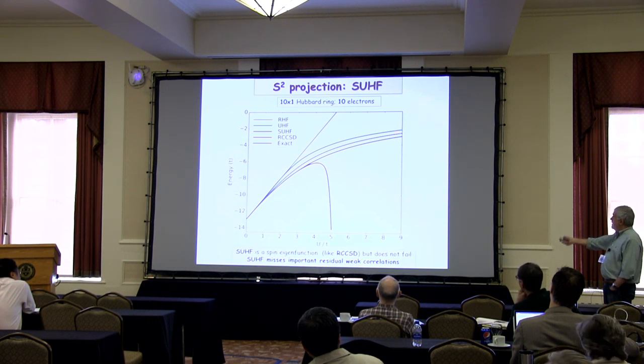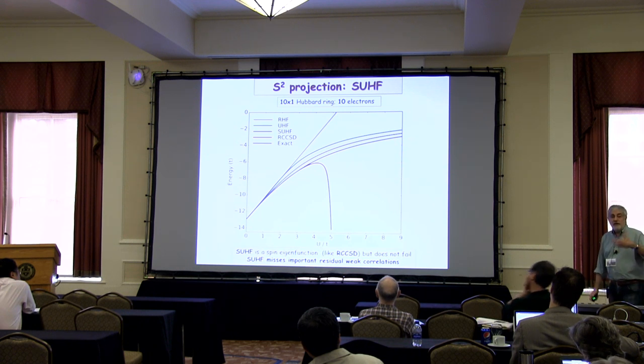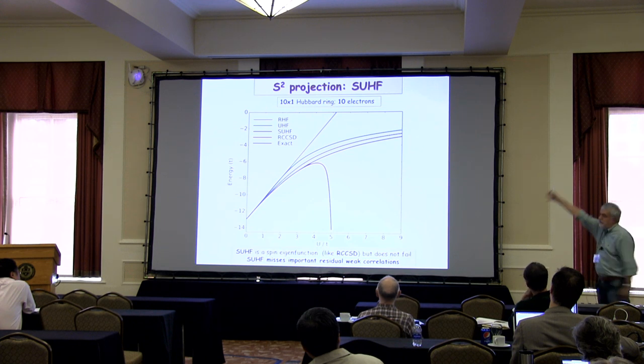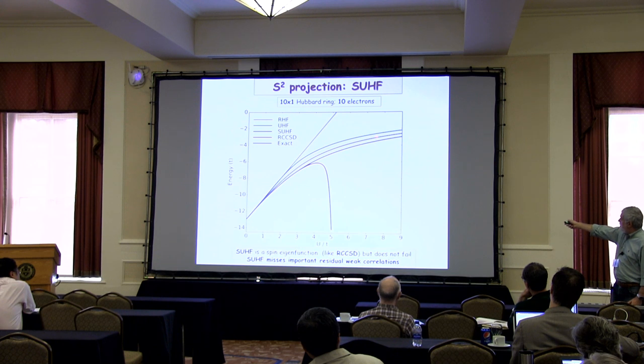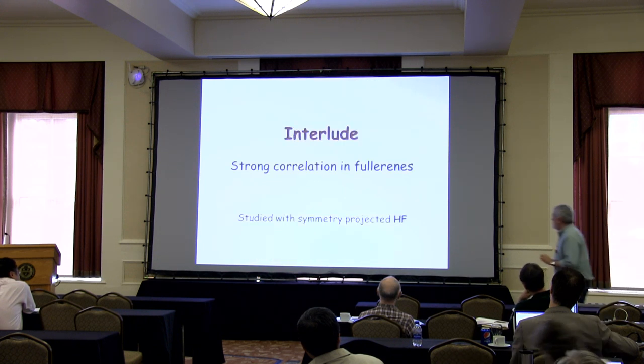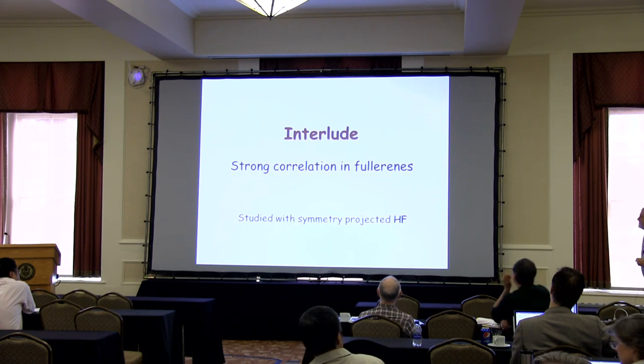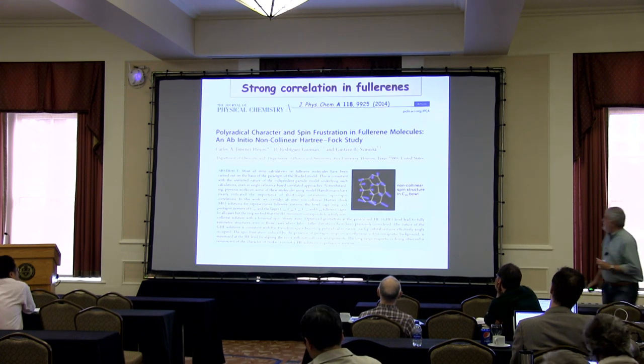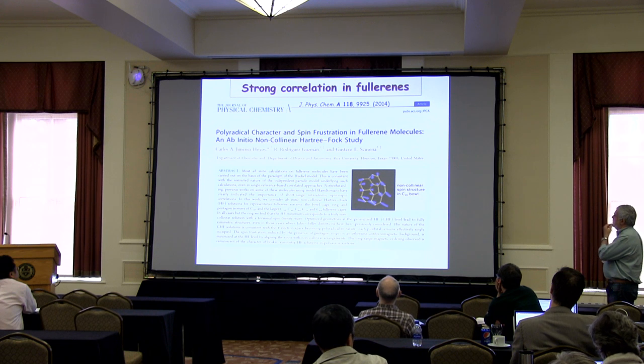doing the strong correlation. And we know that C60, if we dope it with electrons or with holes, it becomes superconducting, which is the same physics as the cuprates in that sense. And I put here some numbers. We actually, in that paper with Carlos, we more or less decided that the Hubbard U for C60 is 3.3 in t units. And if you look at the singlet-triplet gap, it's 1.7 electron volts.